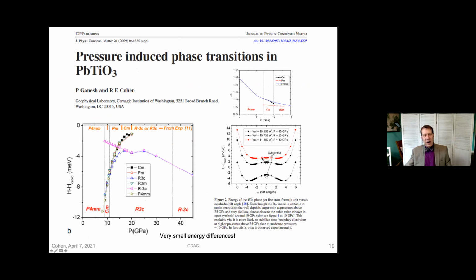And so that's really where a lot of all of this problem comes in, is that it really starts to be a matter of calculational accuracy, of understanding exactly what's happening in these systems. It's a lot easier to study systems where you have big changes, but when you have small, subtle changes, it's hard. On the other hand, the reason that ferroelectrics are useful is that they're very sensitive materials, and that means that they have very small energy differences between one state and another. And so the fact that they're interesting and useful is the same reason why they're hard to study.